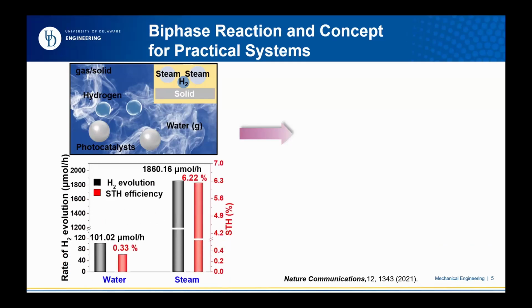So just to give you an example here. If you use liquid water, your efficiency here, I should emphasize this is particle based, solution based, so conversion is typically low. The highest so far to my knowledge is 5.9%. Okay, it's different from a photovoltaic cell based one, where you can reach about 30%, but this is not. And you can see the typical one here. I should emphasize this is based on cobalt oxide. We didn't optimize any catalyst here, just to see what happens when applying liquid water versus steam water. So you can see that efficiency increases very largely, not 20%, it's 20 times, sorry, a 20 times increase in efficiency.